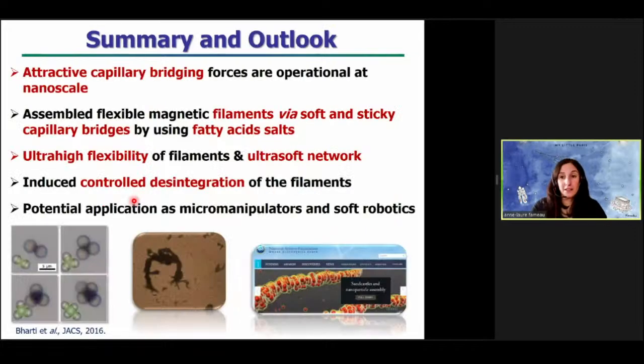So I hope that I convinced you that you can really use capillary forces at the nanoscale to bind, for example, nanoparticles. And by using fatty acid soap, you can really have very soft and sticky capillary bridges that lead to ultra flexible filaments and ultra soft networks. And these capillary bridges based on fatty acids are thermoresponsive, so you can control the disintegration and the formation of this kind of filaments. And the potential application of all this system is as micromanipulators and soft robotics. I showed you two examples with the self-repairing network and the micrograbber.